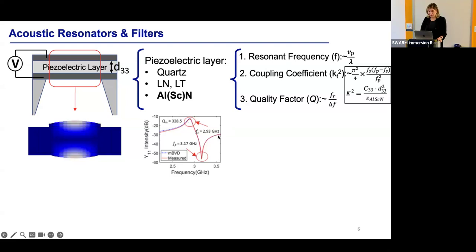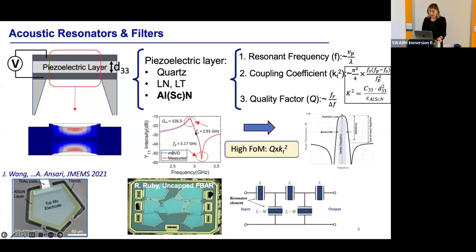Now, the metrics of these resonators, which are the building blocks of our filters: one is obviously the resonance frequency. How high is it? How high can we push it to be? And then the coupling coefficient, which has to do with the piezoelectric properties of your material. So there's always this quest for going after materials with higher and higher coupling coefficients. This coupling coefficient will define the filter bandwidth, as we will see later. And then the quality factor, which is inversely proportional to the loss in your resonator, showing how steep or how sharp this peak is. So once we have these building blocks, what we care about is this figure of merit, which is Q times the kt squared, the effective electromechanical coupling coefficient.